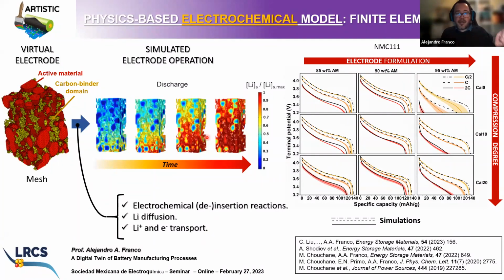So as a function of the C rate, which is related to the current density being applied to the battery, and as a function of the temperature and other operation parameters. And here you see that the model is able to predict also electrochemical descriptors. Here you see discharge curves for different C rates, for 3 C rates, for different electrode formulations and for different compression degrees upon calendering. And you see a very good agreement with experiments. Without changing any internal parameter in the model related to these 3 physical, chemical, or electrochemical processes taken into account, the model is able to follow the trend observed at the experimental level.